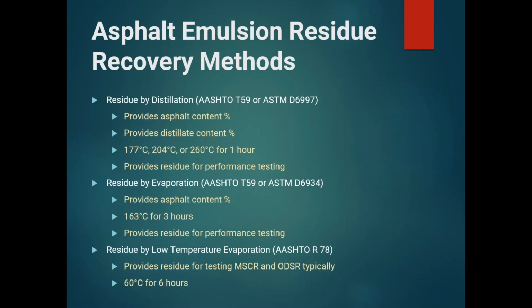And then one of the newer methods for recovering residue is called low temperature evaporation. And this recovery method is really trying to simulate what happens when you take an emulsion out and you put it on the road, and the lower temperatures that the asphalt emulsion itself will be subjected to. Basically a thin film is drawn down on a silicone sheet, and then that's put into a 60 degree C oven for 6 hours to give you a smaller amount of residue that's usually used for testing like the multiple stress creep recovery and original dynamic shear recovery.